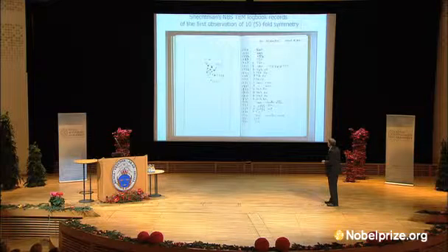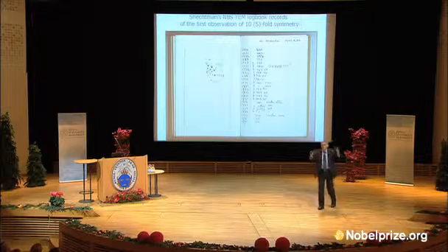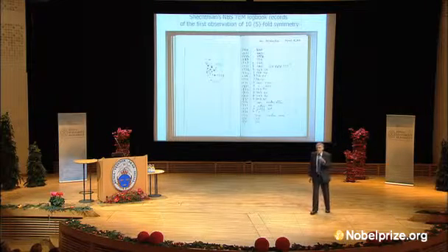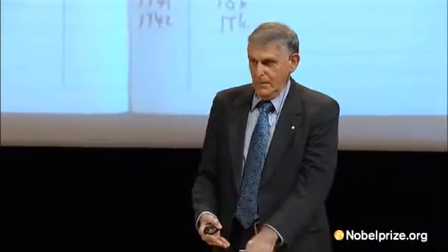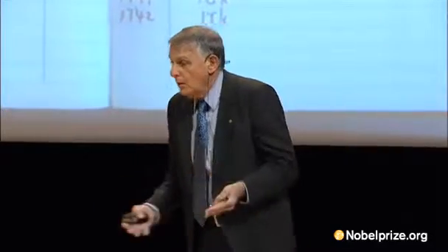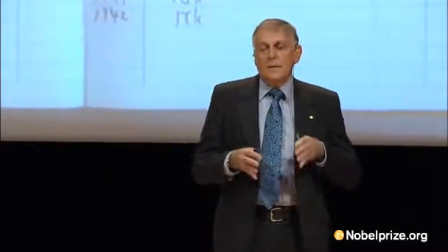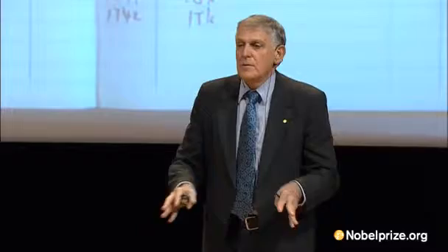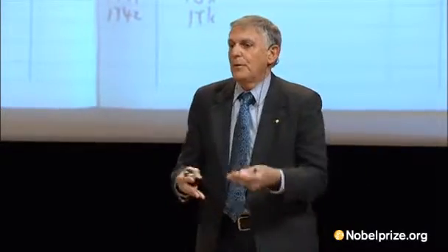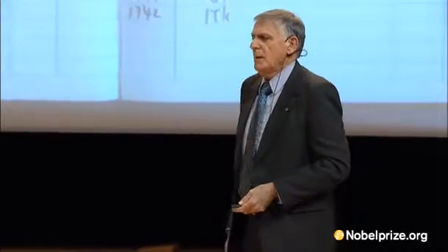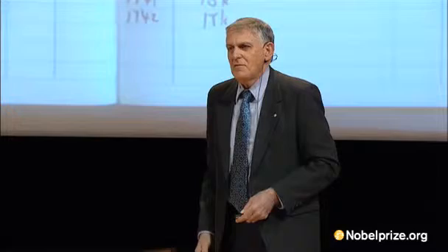1724, 36,000 times magnification, and I see crystals which are pitch black. Pitch black can mean two things. Either the specimen is so bad, that it is so thick that the electrons do not go through, or that the crystal diffracts electrons so intensely that the transmitted beam is left with very low intensity, which was the case. And I was telling myself, hey, that's quite an interesting crystal.